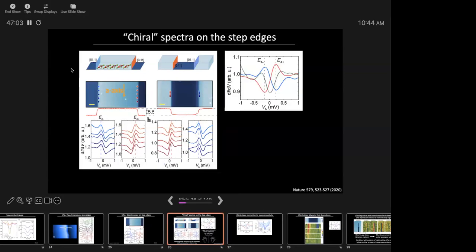Before I should tell you the problems. Here's the superconducting gap, and here are the two spectra on the two step edges. And let me just tell you, even if I separated these by hundreds of nanometers, where the coherence length is nanometers, you would still see the same thing. So this happens on length scales way above the coherence length.